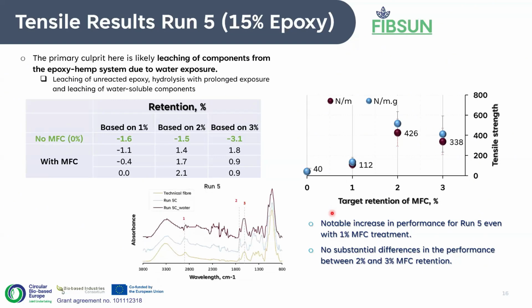So just to buttress again the point with regards to issues with MFC incorporation, I bring forward again what we noticed, the main reason why we feel that this retention is also not justifiable by just simply measuring the weight before and after. Here we find the technical fiber itself before the use of technical fiber in non-woven. And in this case, when we introduce the binder, we have a peak, which is synonymous with epoxy. In this case, with dilution with water, we see that this peak is basically attenuated. And so we say for sure that it's an effect of non-bound epoxy resin in the non-woven.